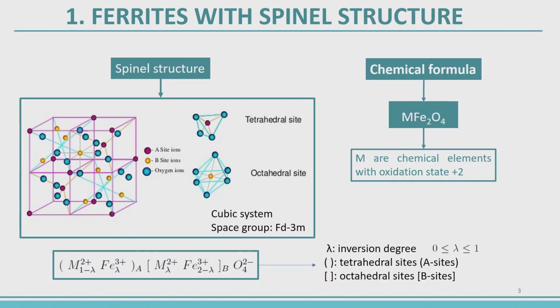This is with the spinel structure, a cubic system with this space group. This is the chemical formula. Here M are chemical elements with oxidation state 2+, and we have iron and oxygen. And then we can also write the chemical formula in this way, in which we explicitly write down the cationic distribution in the tetrahedral and octahedral sites, and this is very important. And here lambda is the inversion degree with range between 0 and 1. You notice that lambda is related with the concentration of iron in the tetrahedral site.